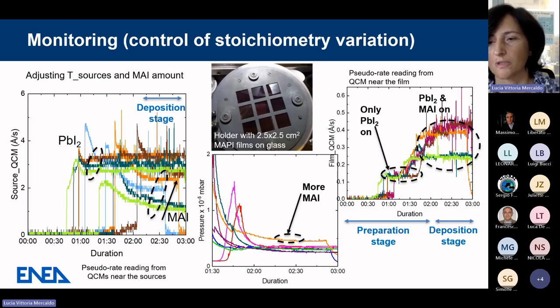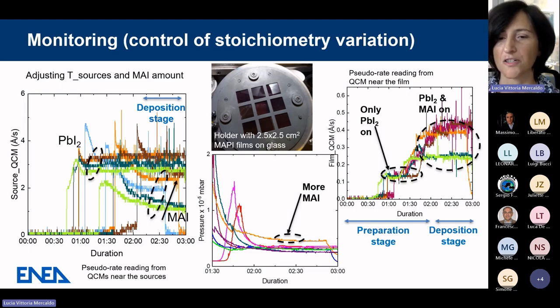This is an example of what one can do by monitoring. So one can control what is going on about the stoichiometry of the films under preparation. So parameters that we should look at and really monitor are the pseudo rate near the sources, the inorganic and organic sources, and the pseudo rate readings near the substrates. I don't go into details because you here see many curves, but just monitoring this, one can keep track of what is going on and adjust the conditions.